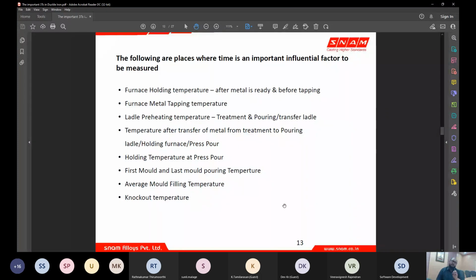So a small assumption, a miscalculation, a wrong measurement, or not measuring the tapping temperature is going to give you no clue about what is going to come in the future. Maybe there can be a loss, or a defect coming up in a particular heat pouring, where you do not have a reference tapping temperature to stratify or to reason out why the defect would have come up. So tapping temperature plays a major role, and measuring it plays a role, and having close control over a given range, or minimizing the range of tapping temperature, plays a major role.